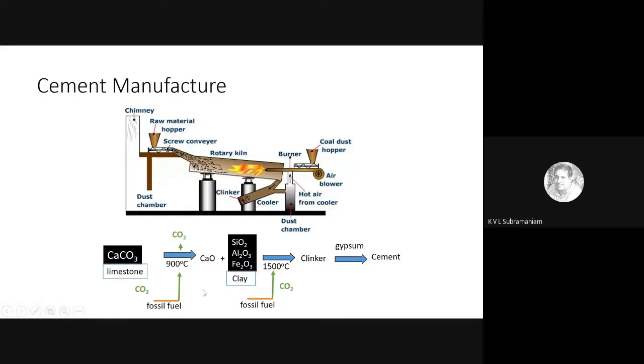Now, if you look at this process, the carbon footprint of this material is associated with the fossil fuel that I burn. I have to burn something to produce a high temperature, because I need temperatures in the range of 1500 degrees Celsius to produce this fusion between calcium and silica, or calcium and alumina. So to produce that, I need to burn fossil fuel. That gives off carbon dioxide, because most of our fossil fuels are carbon-based, whether in the form of diesel, petrol, natural gas, or coal. They're all carbon-based, and when you burn them, you produce carbon dioxide. And the calcium carbonate, when it decomposes, of course, gives off carbon dioxide. So these are the two sources of carbon dioxide emissions from cement.